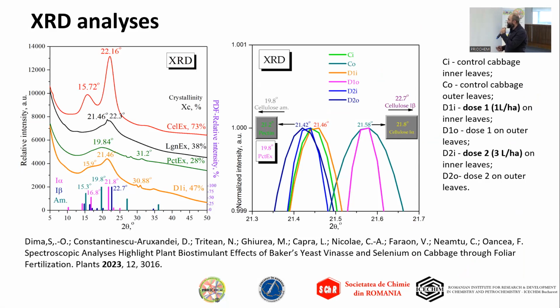We used two doses of selenium biostimulant applied by foliar fertilization on cabbage, and we compare the samples by XRD analysis. First of all, we compare the cabbage sample. We can see it's a convoluted signal between cellulose, lignin, and pectin, with cellulose 1 alpha as the main signal. Actually, this is the first XRD fingerprint.